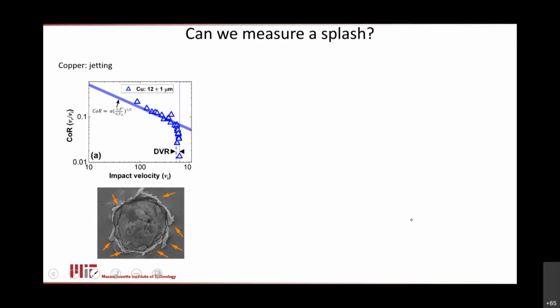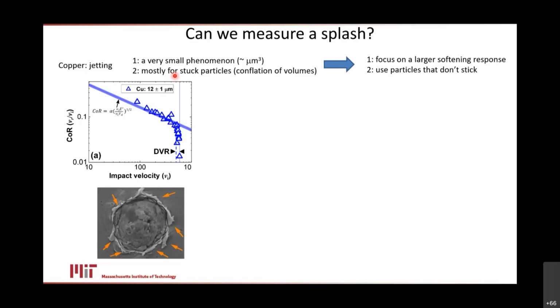And so we started thinking about that. How do you do it? In the case of copper, it's very hard to do because it's so small. We're estimating something like a cubic micron of matter gets ejected. It's just very tiny. And of course, there's a conflation of all the different volumes because the particles are sticking. So when we went forward with this work collaborating with Livermore, we wanted to design an experiment where we would get a bigger splash that would be quantifiable. And so we wanted to focus on a system with more of a softening response, and we wanted to use particles that bounce away so that they're not part of the math anymore, and we can isolate just what's happening on the substrate.